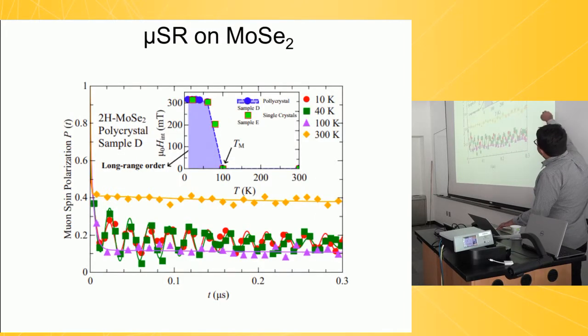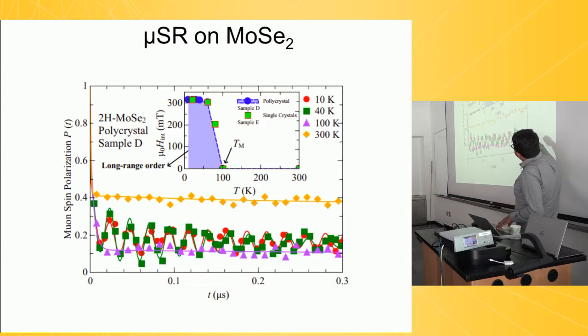Here's the same data on moly diselenide. Once again, you see oscillations at low temperature. In the case of moly diselenide, these oscillations vanish around 100 Kelvin. And the internal moment is even larger, 300 millitesla.